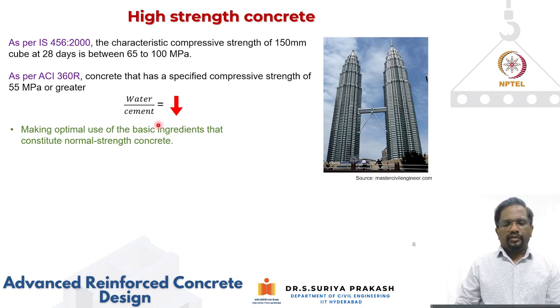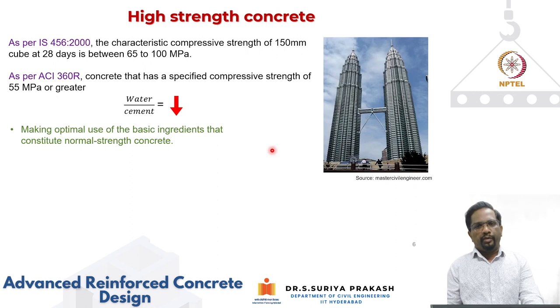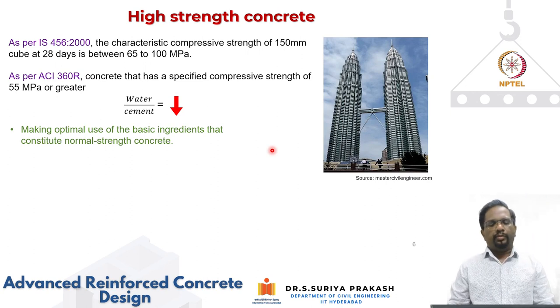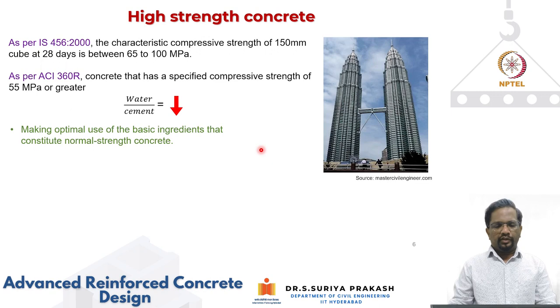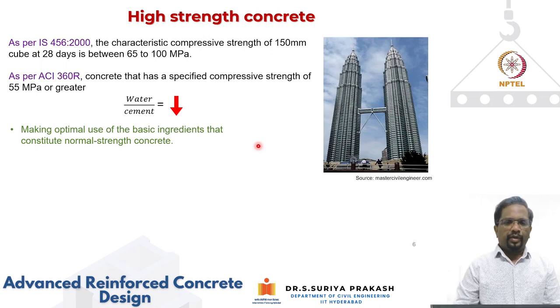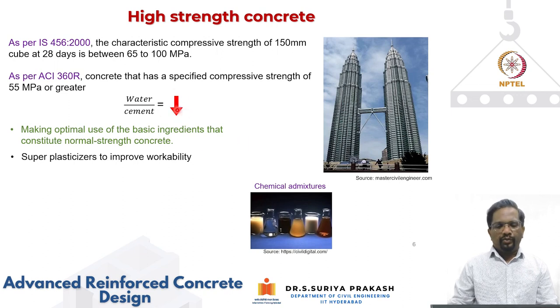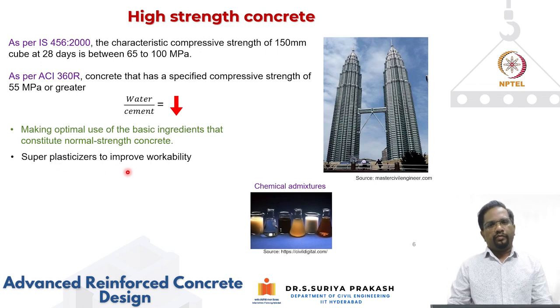So one way to achieve high strength concrete is to use a lower water cement ratio, like the one that we see here. Another thing is making optimal use of the basic ingredients that constitute normal strength concrete. What we have seen in the previous slide, we have cement as a binder, and then coarse and fine aggregate, and we also add chemical and mineral admixtures. All these basic ingredients can be optimized. For example, how do you reduce the water cement ratio? One way is to use chemical admixtures like superplasticizers, so that with a very low water cement ratio, you can still achieve the workability that you want, right? In that way, with lesser water in the system, your strength can be increased.